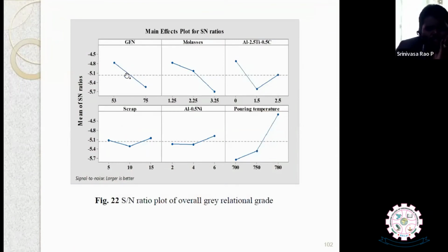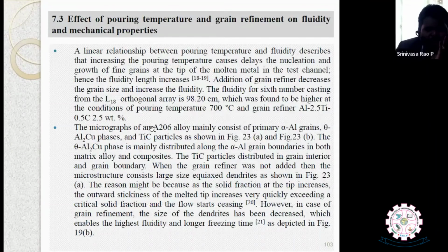Yeah, so these are the graphs you see here, the S/N ratio graphs and the effect of pouring temperature. The linear relationship between pouring temperature and fluidity describes that increasing pouring temperature causes delay in the nucleation and growth of the fine grains at the tip of the molten metal in the tester. Hence, the fluidity increases. He has given the reason why pouring temperature increases the fluidity: it delays the nucleation and growth of the fine grains at the tip of the molten metal. So that is the reason why the fluidity length increases.